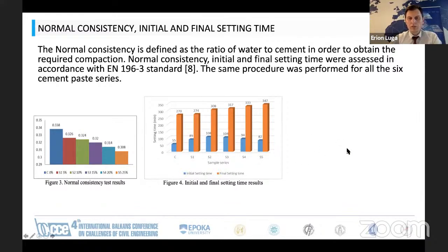On the right, we can see the initial and final setting time results. For the initial setting time, there is an irregular result, not a certain or linear trend, whereas for the final setting time, we can see an almost linear trend, which shows that by increasing the slag amount, the final setting time also increases.